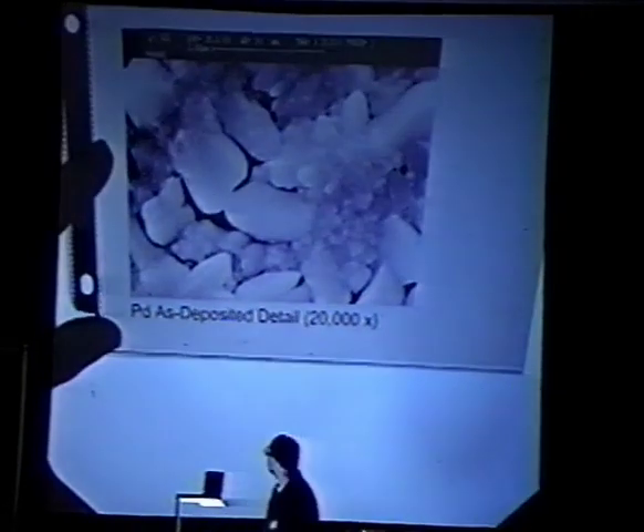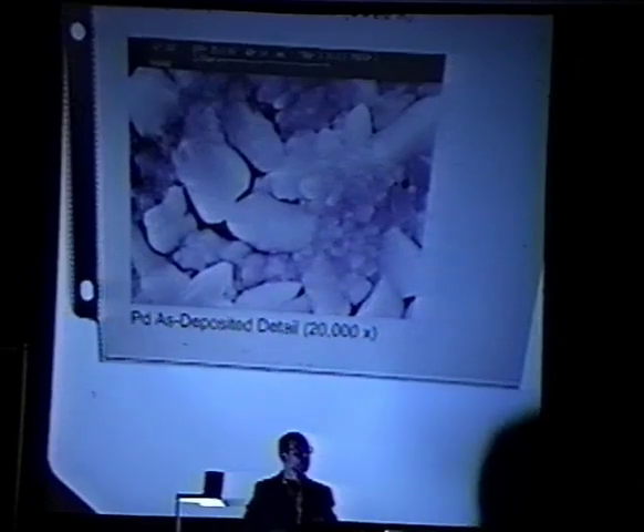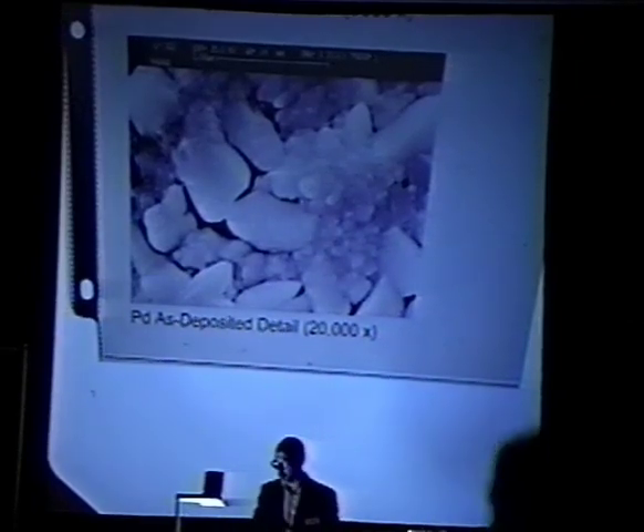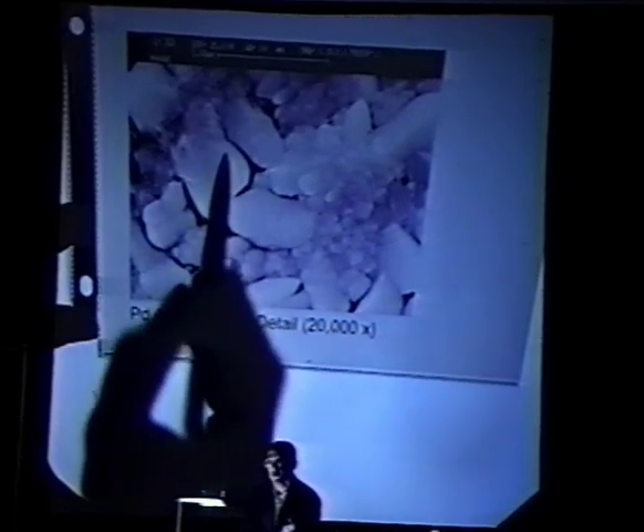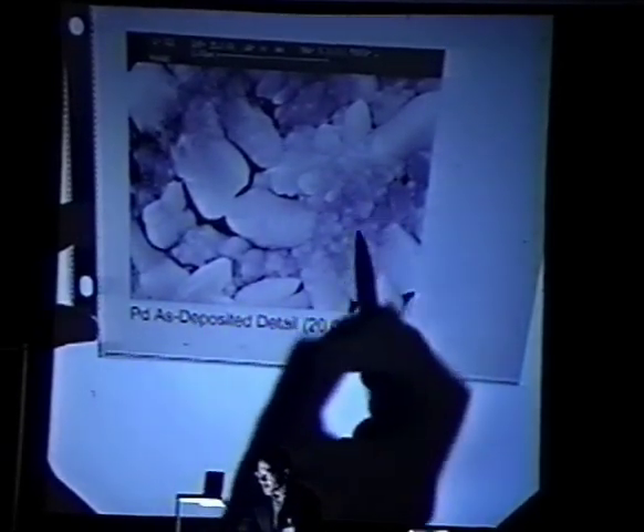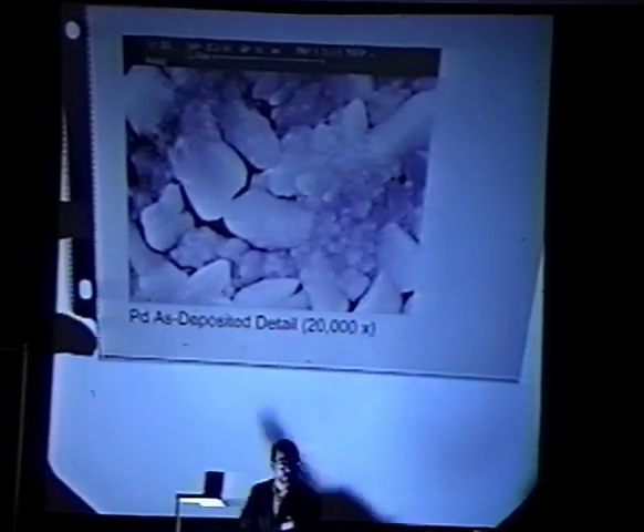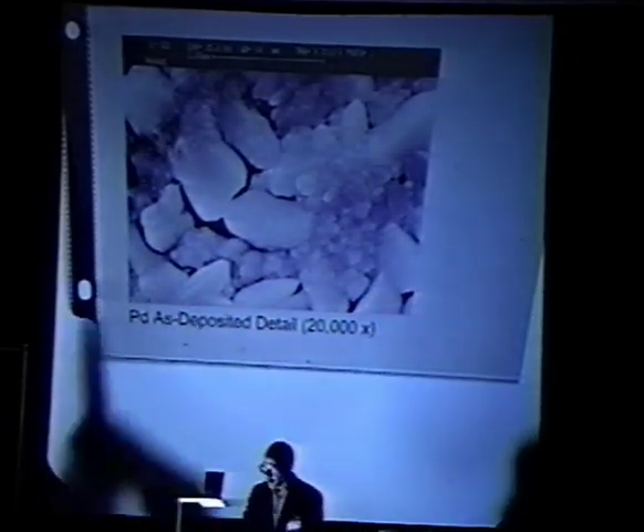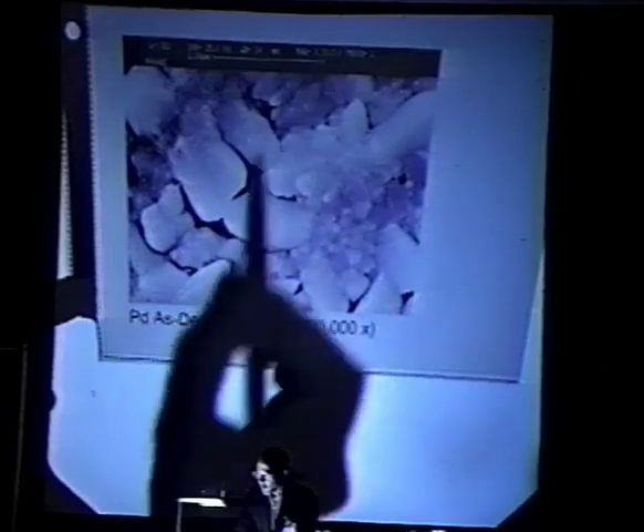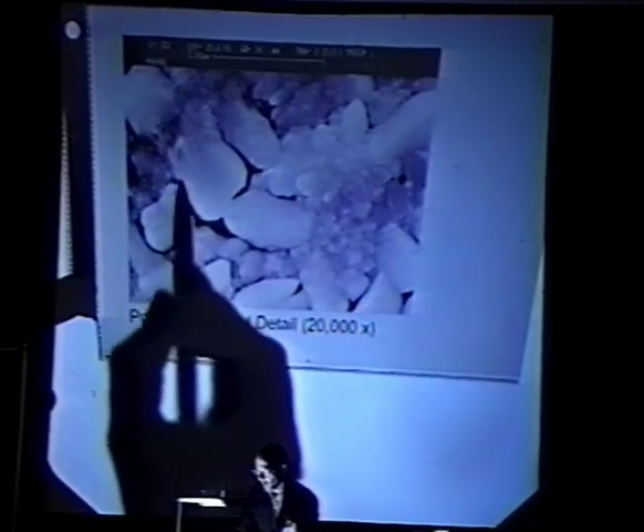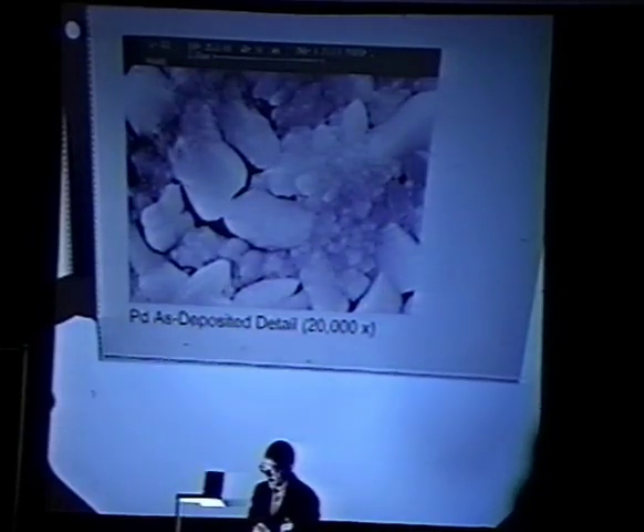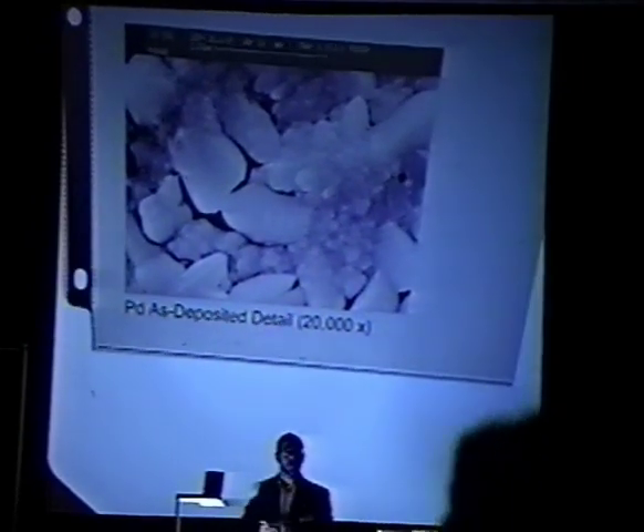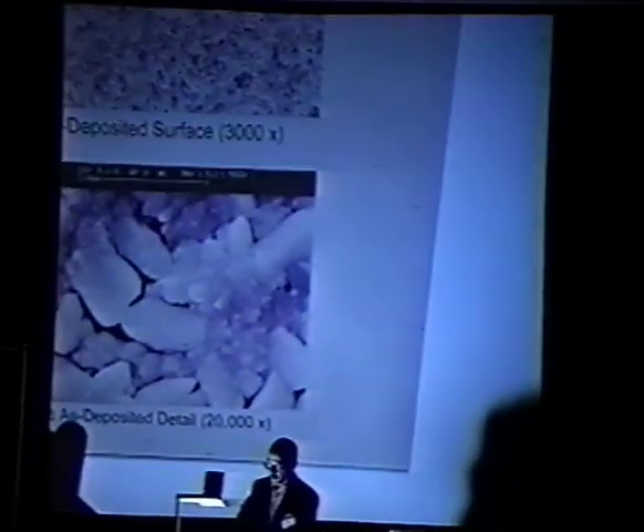What I did was take this 10 microns and blow it up, took another one at 20,000 times magnification. And this one has a pretty good detail of what the grains look like. You can imagine the amount of surface area that's embedded in this. What you see are some of these larger grains that have started to grow, and then a whole bunch down in here that are very, very small, incredibly microcrystalline. So it's somewhere between an amorphous and microcrystalline type of structure. Again, this is a 2 micron scale here, so this particular large grain is maybe 1 to 1.5 microns across. That's typical as deposited, right out of the deposition chamber, of what they look like.